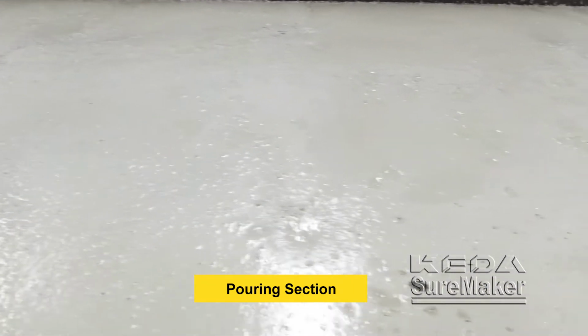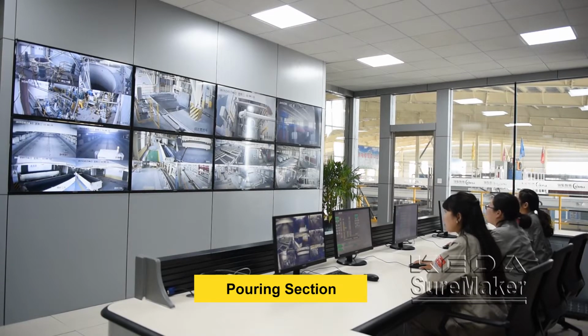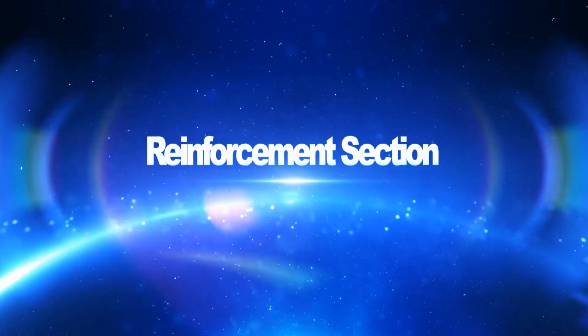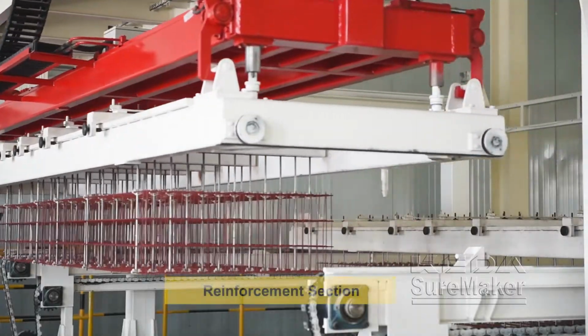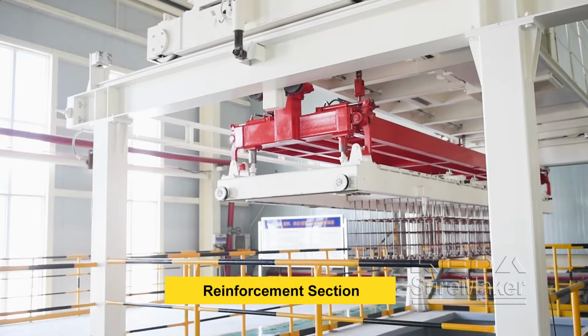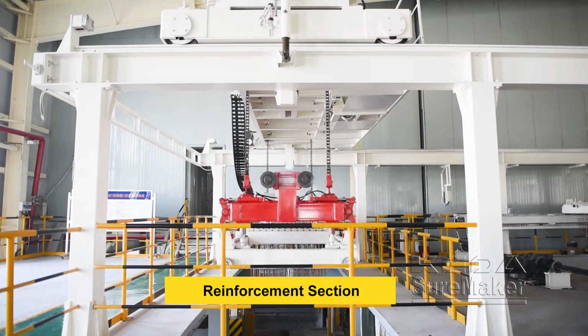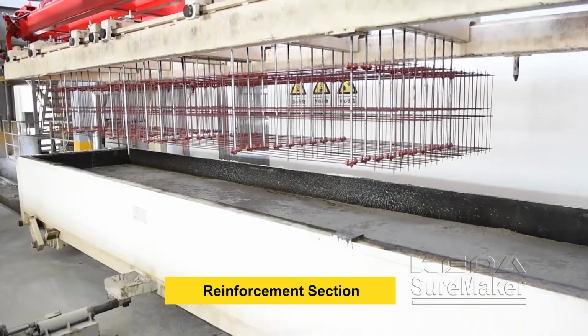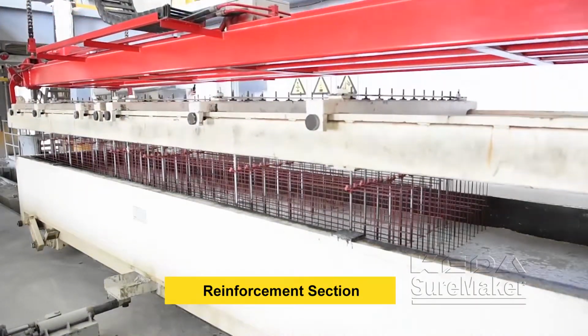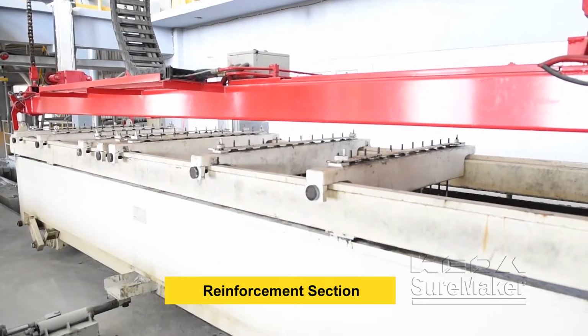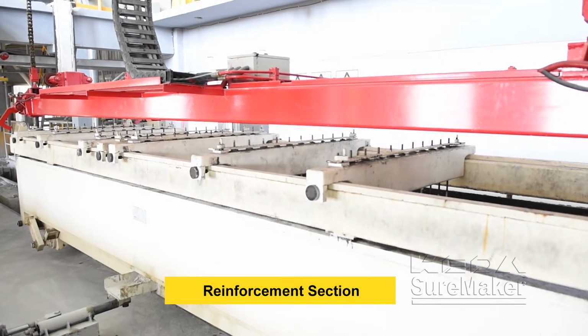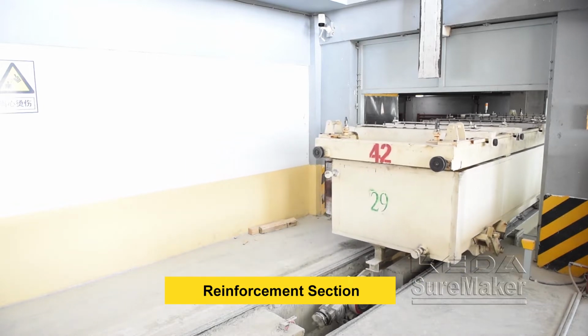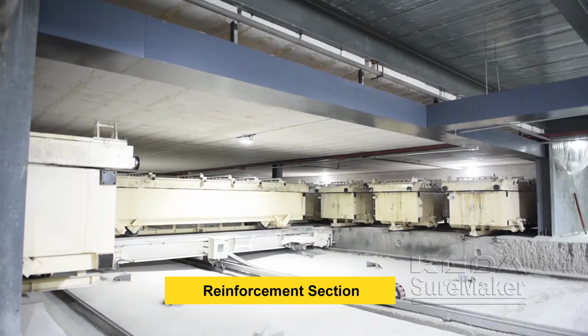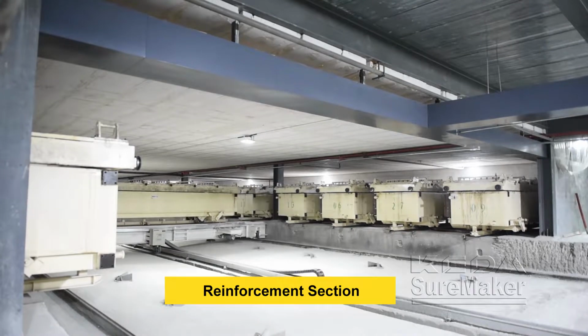The automatic batching control system ensures the accuracy and reliability of batching operation. After pouring, the steel mesh cages are inserted into the slurry by the saddle frame and then transported by ferry car to the pre-curing room. The temperature of the pre-curing room is around 40 to 45 degrees Celsius.